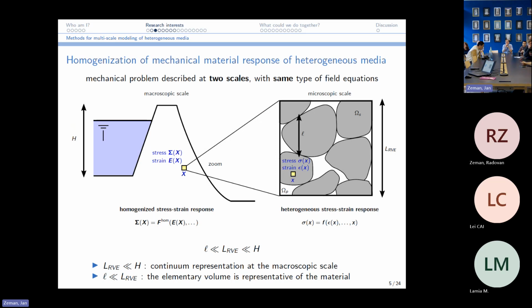So one of my activities is to determine this homogenized stress response from the microstructure information and the information about the local stress strain response of each of the constituents. And for doing so, we use multiscale methods or micromechanics, and we have to assume that at any point of the macroscopic level, we can define some representative volume element, which is much smaller than the fluctuations of the fields at this scale, and which is much larger than the sizes of the heterogeneity at the microscopic scale, which is a usual requirement, but sometimes it is not met. And so that is for mechanics. And as you can see, we have the same type of constitutive equations at the microscopic and the macroscopic level.